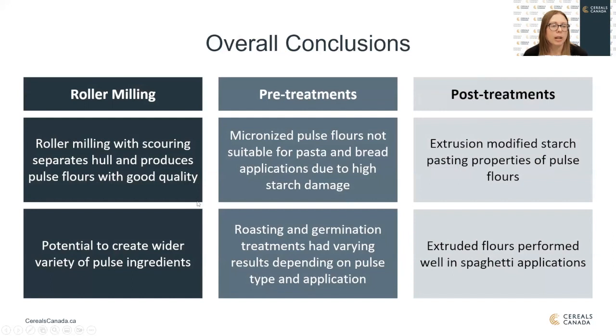So just to point out some takeaways from everything that I've talked about today, roller milling was a good way to produce a high quality flour, and the scouring separated the hull from the flour well. Roller milling also creates the potential to create a wider variety of pulse flour ingredients with those different flour streams. For pretreatments, micronization of pulse flours really did not work well in the pasta and bread applications we tested due to the high starch damage. However, that's not to say that they wouldn't work well in a different application. The roasting and germination treatments had varying results depending on pulse type and application.